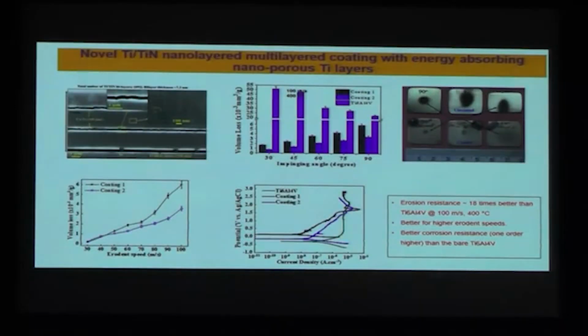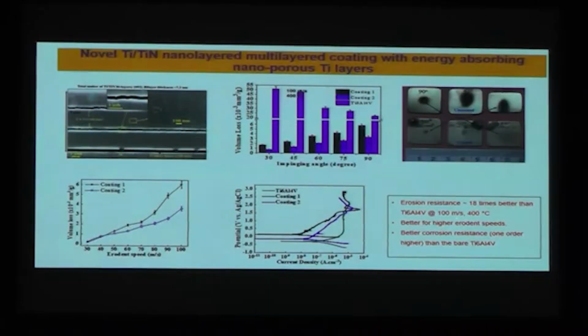And further to that, we have also come out with nanoporous based coatings. The uniqueness of this coating is that it can absorb the erodent energy to some extent, and by that way it improves the erosion resistance. In this case, we have realized about 18 times higher erosion resistance than the bare titanium alloy substrates. So these coatings have the ability to withstand high temperature, erosion, and corrosion. And not only in aerospace applications, they can also be used for many industrial and automobile applications.